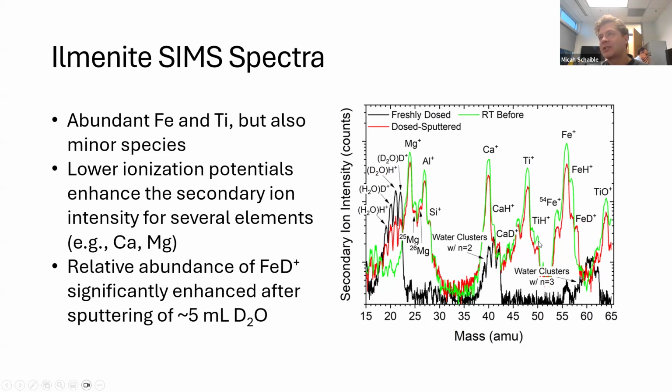We don't see much of a change in the titanium signal or really any of these other species, suggesting that the water is preferentially interacting with the iron species as opposed to these other substrate cations. So we see, yeah, the relative abundance of that deuterated FeD+ is significantly enhanced after the D2O exposure.